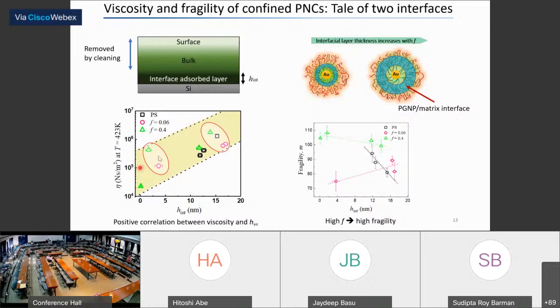Essentially, if I try to summarize in this plot, you see a correlation between viscosity and the interfacial thickness, and this is across all these samples, including the pure polymer film, where there are no particles. In other words, you can control the viscosity by controlling the interfacial thickness. So even irrespective of what the value of F is, there is an additional parameter which is actually controlling the viscosity. On the other hand, if you look at another parameter, for example fragility, you see that also has a dependence on this interfacial thickness.